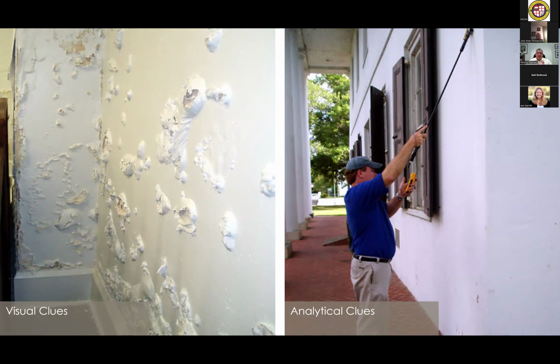The plaster is still dissolving and breaking down, bubbling up, and causing this sort of skin cancery look to the interior of the building. So we try to figure out why. What's the underlying issue, and why is it misbehaving? And obviously, since this is an extreme example, something has changed, right? This is not the way a building normally responds. And what has changed is that somewhere along the line, they put a Portland cement plaster on the outside and a Portland cement plaster on the inside. And so that's trapped all the water inside this 1840 brickwork, and it has nowhere to go. And it's still looking for a place to evaporate. So it's just going to keep climbing up until it finds a place where it can get out. And so that's what we're trying to figure out, the whys.